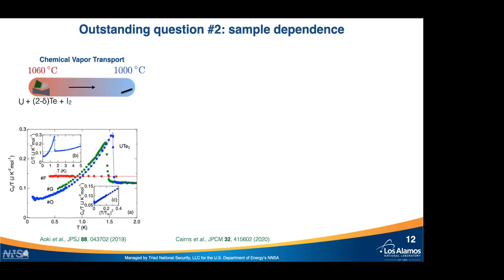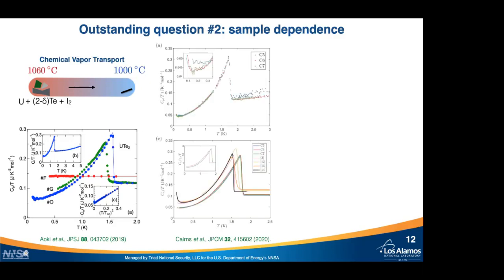We don't know yet. There is an early heat capacity study comparing chemical vapor transport samples that I just mentioned to you with flux samples. So here the red circles are data from a flux grown sample, and there is absolutely no superconducting transition temperature. So there's clearly something going on there. More recent results showed a spread of TCs depending on the initial tellurium concentration, for example. We also know that depending on the thermal gradient, that can change too. The interesting point of this recent paper is that TC scaled with gamma.